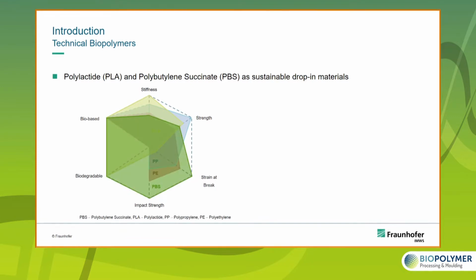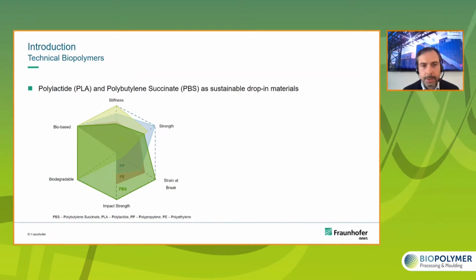However, there are other biopolymers entering the market right now, and one of the most interesting of those is PBS, polybutylene succinate. And here you can see that this material has very good ductility, so high strain at break, high impact strength, and is also bio-based and biodegradable. And especially in combination with PLA, there are many options to design and to compound polymers and mixtures which can easily compete with polyethylene and polypropylene.